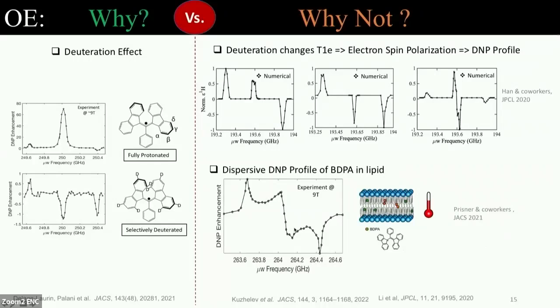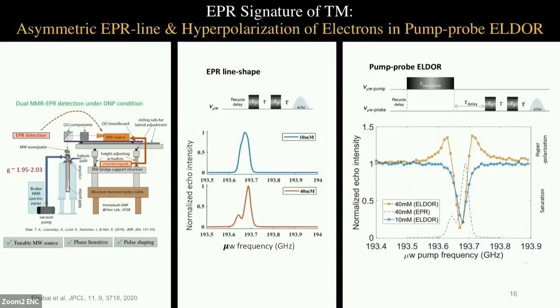So all these things that I have shown you right now are all based on NMR detection. We can infer what might be happening to electrons, but we do not know exactly from these profiles. In order to understand what might be happening to the electron spins, we did some EPR measurements of these radical systems. It was possible through a DNP instrument, which could also do EPR detection at the same condition. In our EPR measurement, we found that the radical system which gives rise to thermal mixing DNP has an asymmetric profile, and that's needed in order to generate a polarization difference.